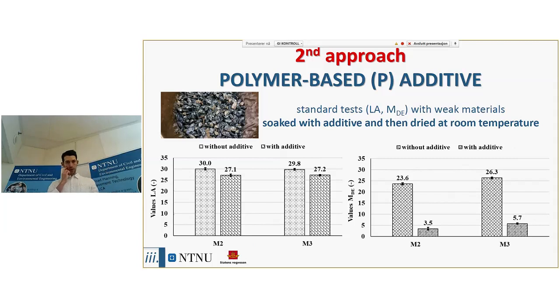That is to say, the Los Angeles test and the Micro-Deval test. And as we can see from these pictures, it seems that these additives do have a beneficial coating effect.